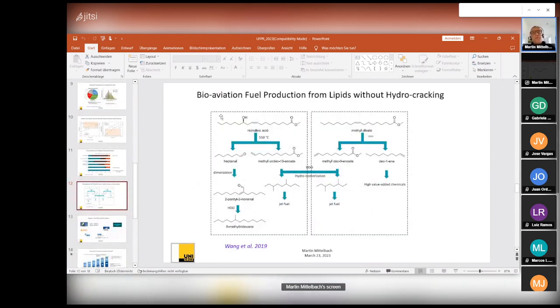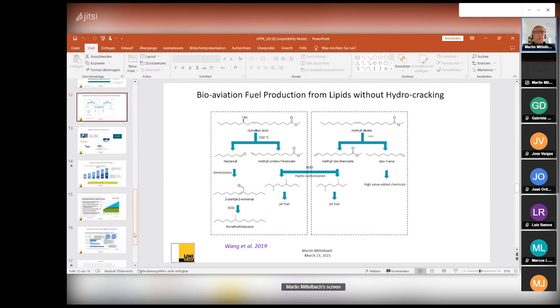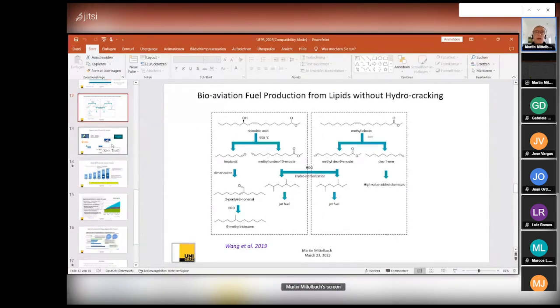You can also get bioaviation fuel from lipids without hydrocracking. For instance, from castor oil, which contains about 50% ricinoleic acid. If you make reactions up to 560 degrees, you get jet fuel by cracking and isomerization, or also from the major fatty acid from oilseeds, oleic acid. You can also produce products without any oxygen, which could be used directly as fuel. But these fuel technologies are actually not available.